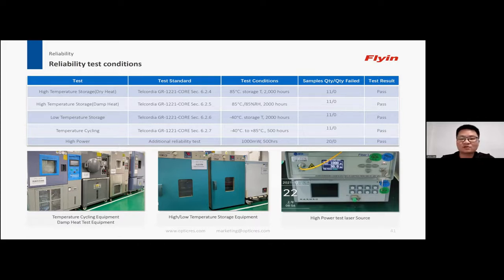And the second one is high temperature storage, but damp heat. That means the temperature is 85 degrees centigrade and the humidity is 85%. And it also takes 2,000 hours for test. And the third one is low temperature storage. The temperature is -40 degrees centigrade, and we have to put everything inside for 2,000 hours. The last one is temperature cycling. The temperature range is from -40 to 85 degrees centigrade, and the test takes about 500 hours. And last one is high power.